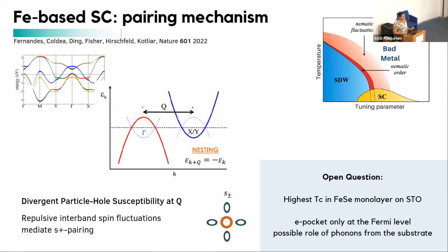What about the pairing mechanism? So in this band structure, you can see that there are these gamma, X and Y pockets that are actually connected by a nesting vector. And this nesting vector is the one that is characterizing the symmetry of the spin density wave, the magnetic state found in the undoped compound. So the nesting effect is inducing a divergent susceptibility at this Q point, and the spin density wave is realized in the undoped system.